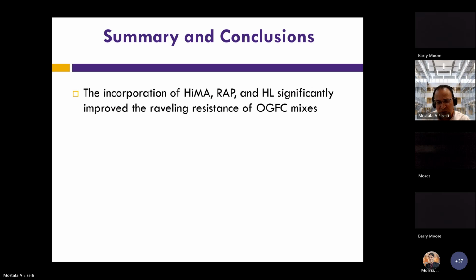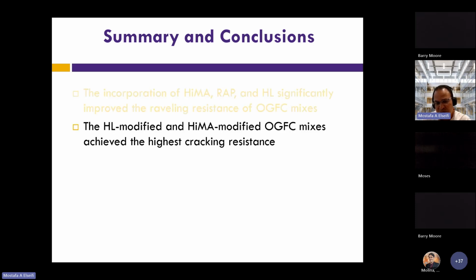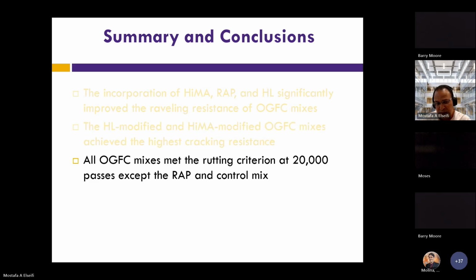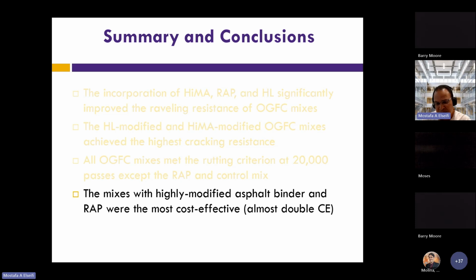So in conclusion, we found that the incorporation of HiMA, RAP, and hydrated lime significantly improves the raveling resistance of the mix. Also, the hydrated lime and HiMA achieve the highest cracking resistance for the mix. All the mixes met the rutting criteria at 20,000 passes except the RAP and the control mix. And the mix with highly modified asphalt binder and RAP was the most cost effective. You can see there was a very clear distinction in cost effectiveness.